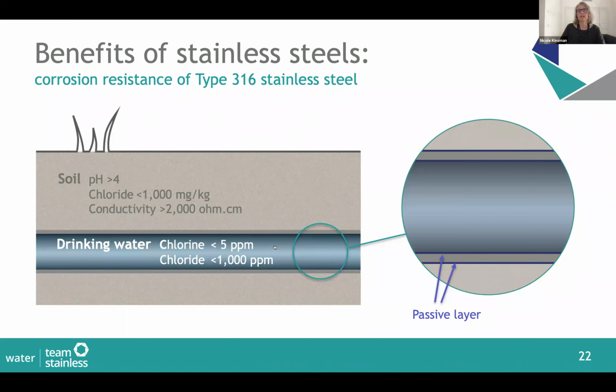So self-passivation, that's the secret behind the corrosion resistance of stainless steels. A thin passive layer protects the stainless steel, and that passive layer depends mostly on chromium, but also on other alloying elements such as molybdenum, etc. There are different stainless steels with different levels of corrosion resistance, and one that has quite a good level of corrosion resistance, particularly for soil and water, is type 316 stainless steel. So it resists soil corrosion in these conditions.